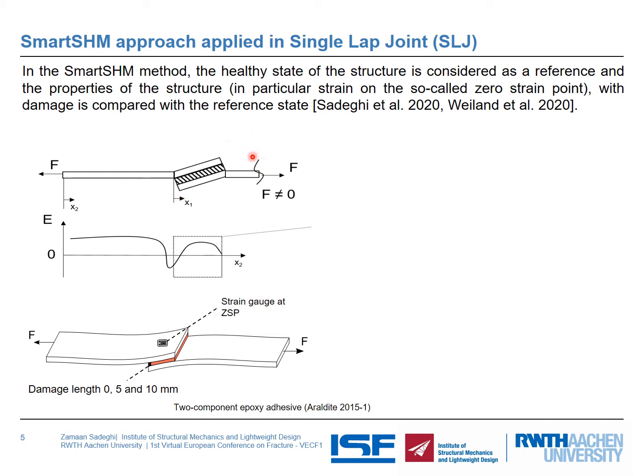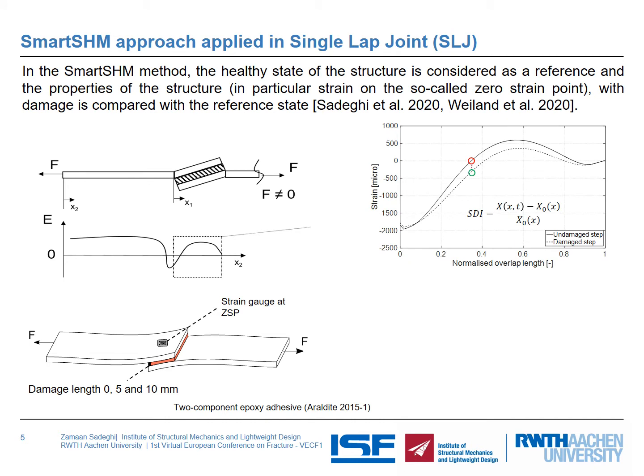So if we consider a single lap joint, the stress state on the single lap joint creates such a strain variation on the adherent over the bonded area, in which there is always a point with zero strain value. If we consider the strain variation again over the bonded area, we can easily detect this zero strain point. This zero strain point is not dependent on the applied load as long as damage has not occurred in the structure. Once damage has occurred in the structure, the former zero strain point gets some value, and the comparison between the undamaged and damaged states can create a structural damage indicator.